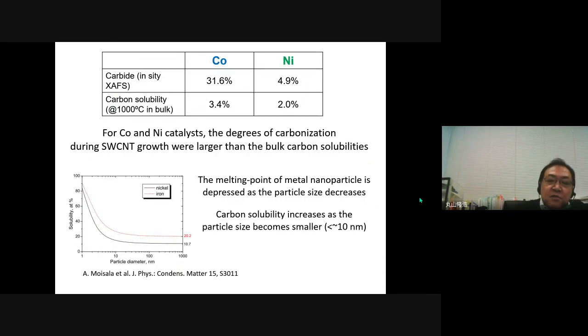So it should be noted that for cobalt and nickel catalysts, the degree of carbonization was higher than the bulk solubility. It is well known that the melting point of a metal nanoparticle is depressed as the particle size decreases to nano size. It has also been pointed out that carbon solubility increases with the decrease of particle size. So we consider that such a nano-sized effect occurred for catalyst particles, which results in the increase of carbon solubility. Next, please.